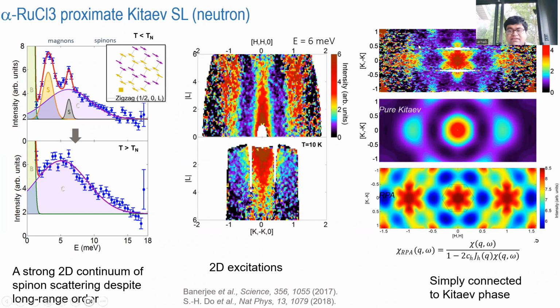started to conjecture. And as we see that we have really two-dimensional interactions, this is another plot that we did in the Science paper where this is the one direction, two inclined directions. So if you look at the scattering in the plane, you get these nice star-like features, which do not quite match the pure Kitaev calculations. So this is essentially quantum Monte Carlo calculations in the pure Kitaev state. We don't quite get that, but if you squint your eyes, you will see that you have a star here. You can also see a couple of stars in the flanks. And that kind of starts to match what you see here. You can see that you have an almost star-like feature coming up here.